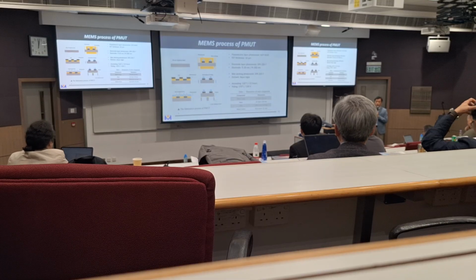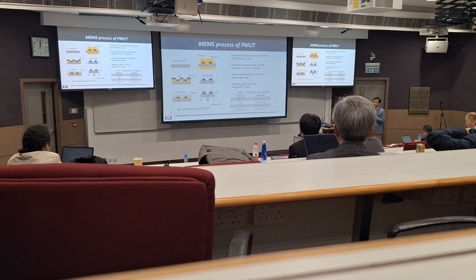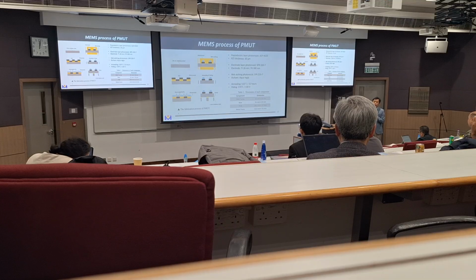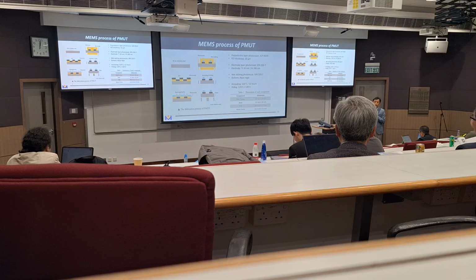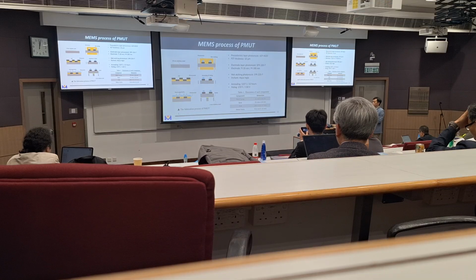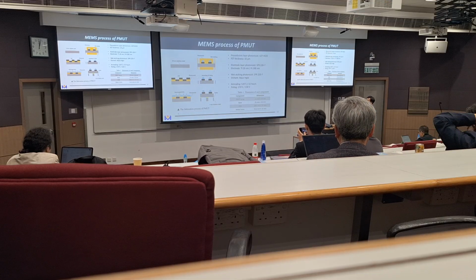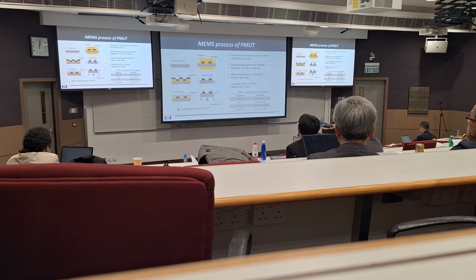because the air-coupled frequency is low. It cannot be too small, or the efficiency is not so good. So our idea is to fabricate a PMUT sensor that's around 1 millimeter in size. But because of the array sensor, we need to make a lot of them. Later on, I will show you we fabricated one with 19 sensors in a single package.